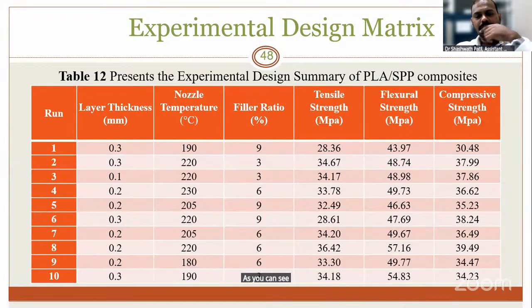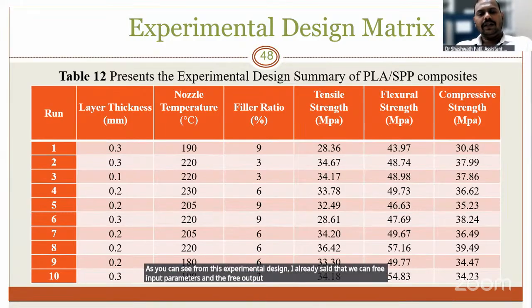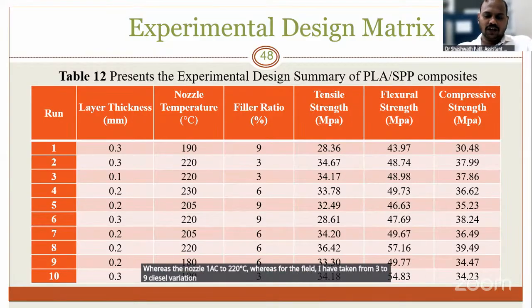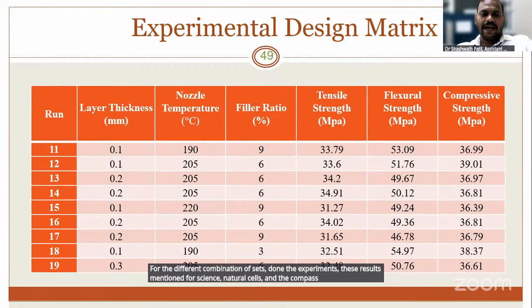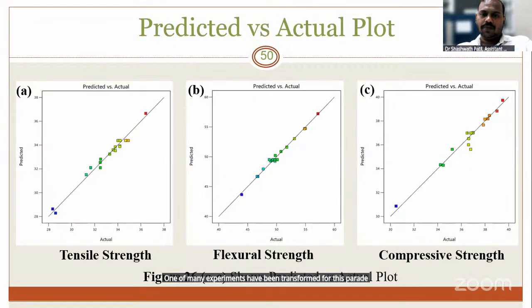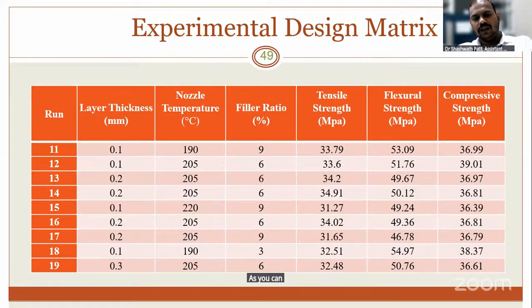As you can see from this experimental design, I have taken three input parameters and three output parameters. For the input parameters, the layer thickness ranges from 0.1 to 0.3, the nozzle temperature ranges from 180 to 220 degrees, and the filler ratio ranges from 3 to 9 percent. For different combinations of sets, I did the experiments and attained these results for the tensile strength, flexural strength, and compression strength. A total of 19 experiments were performed with different combinations, for example 0.1 layer thickness, 190 degrees and 9% filler, and 0.2, 205 degrees, 6% filler. Like this, variants were performed.